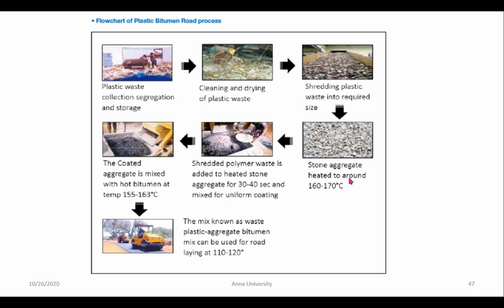So plastic waste is collected, sorted, segregated, then cleaned, dried, and then subjected to the shredding process. Now, after shredding, the stone aggregates are heated to a temperature of around 160 to 170 degrees Celsius, after which the shredded plastic waste is added to it. Now, what happens is at that temperature, the polymer gets softened, and there is a uniform coating of the plastic formed over the aggregate, and this coating takes just 30 to 40 seconds.